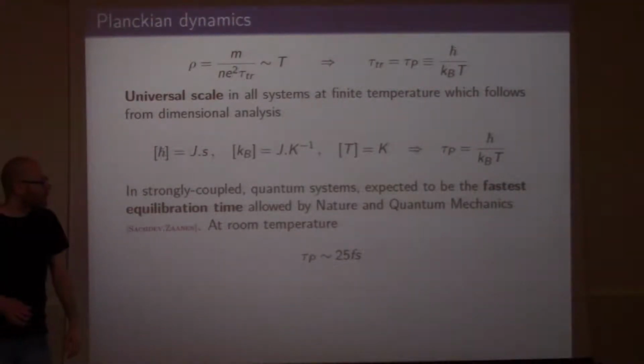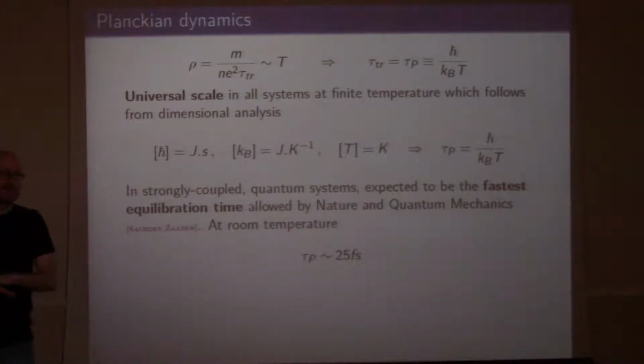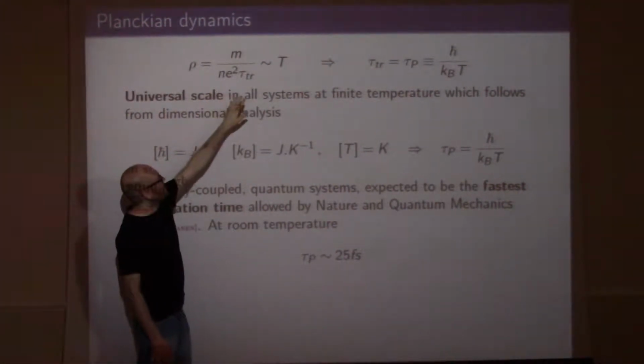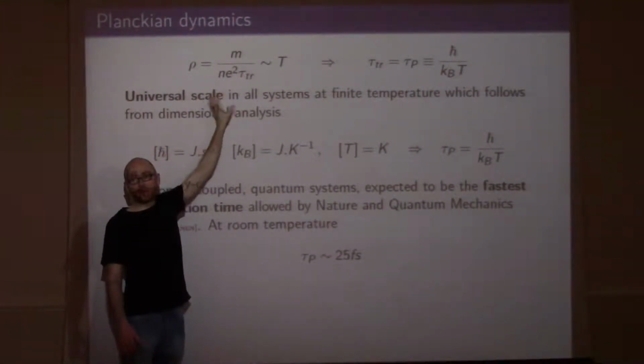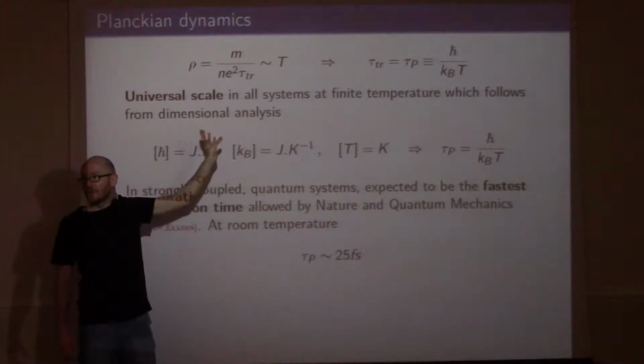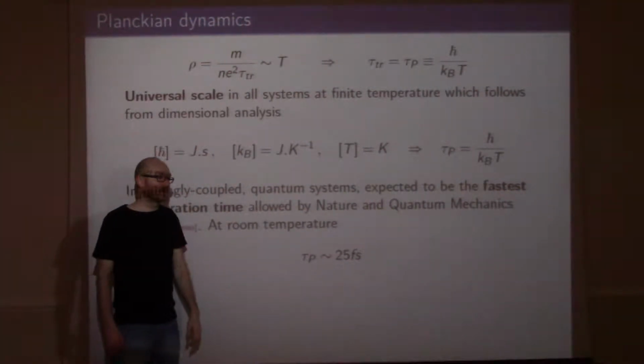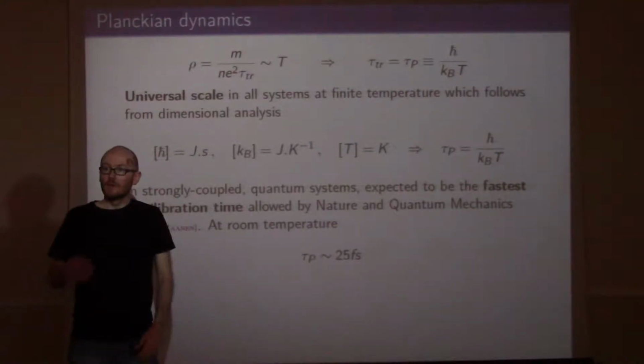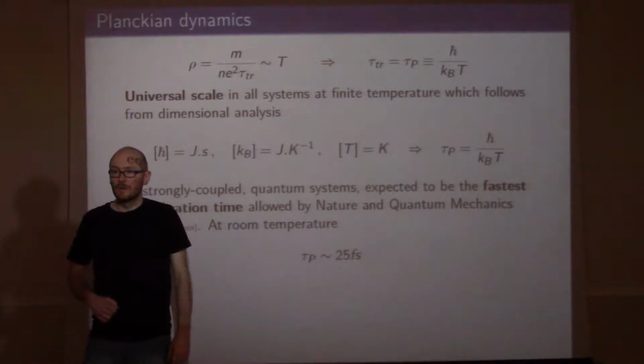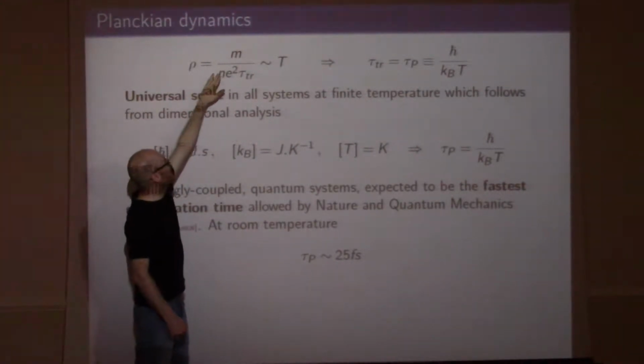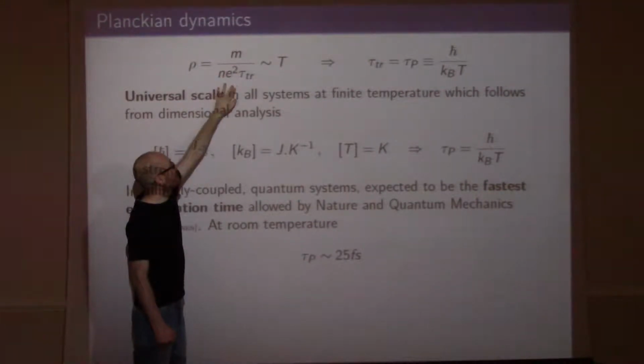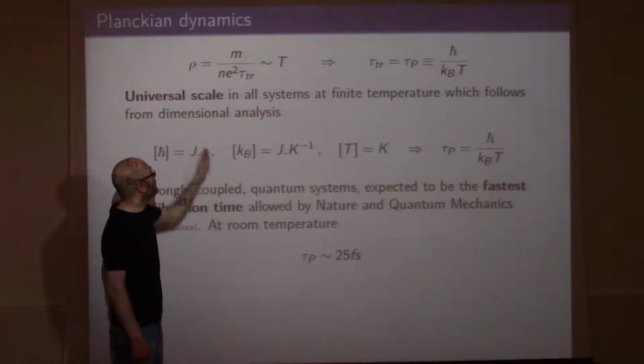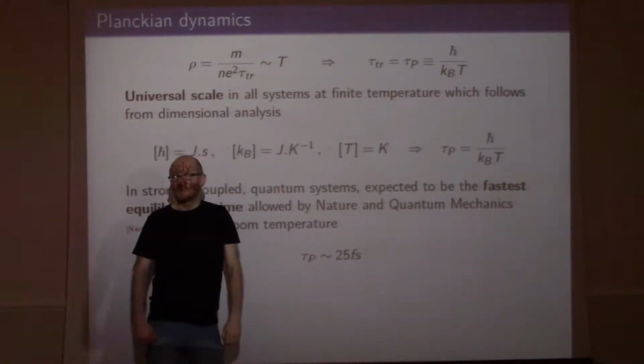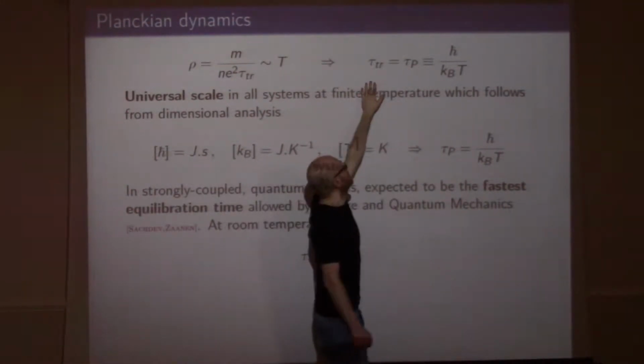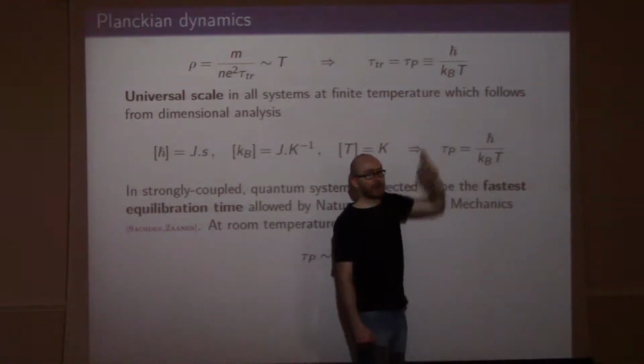Okay, so there's one natural interpretation of this linear resistivity, which may or may not be the correct one, but here goes. You might still insist on trying to interpret this linear dependence in terms of some transport timescale. So then what would you do? You do the simplest thing you could think of. You would write a formula that's similar to the formula we saw in the first two lectures for a metal with a slow momentum relaxation. So this is like some Drude type formula where you have the mass of the charge carrier, the density of the charge carrier, the unit charge, and the transport timescale. And then you would equate that to temperature, because that's what you see in the experiments, and from that you could extract the transport timescale, and you would find that essentially this goes like h-bar over k_B T.